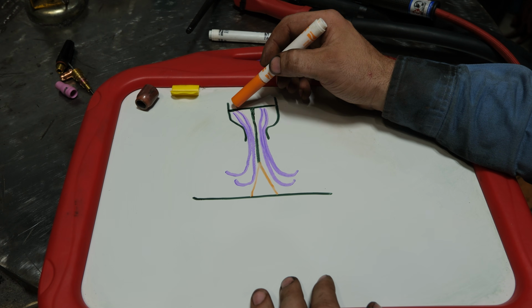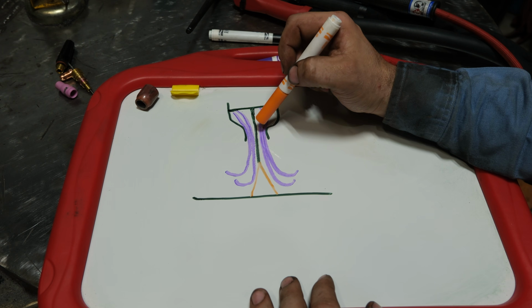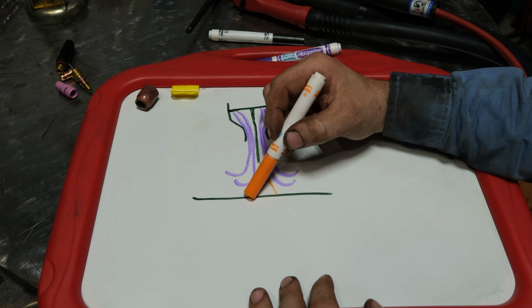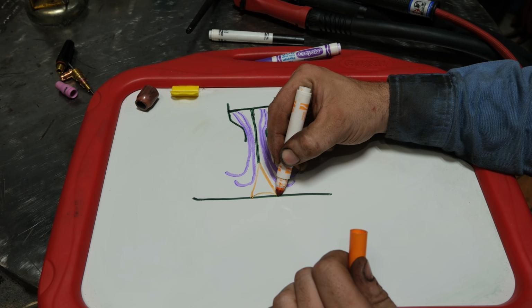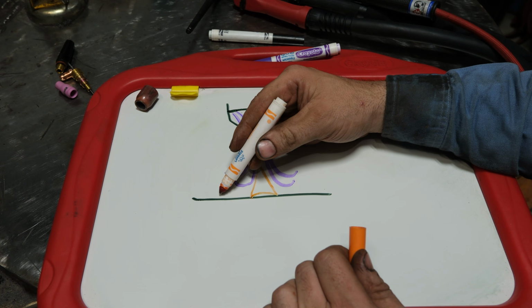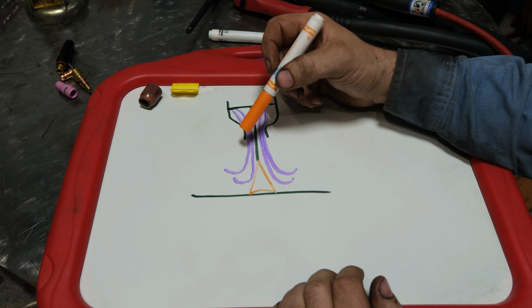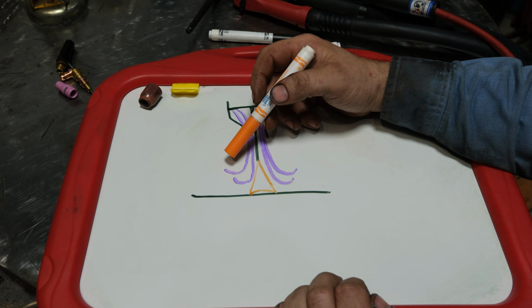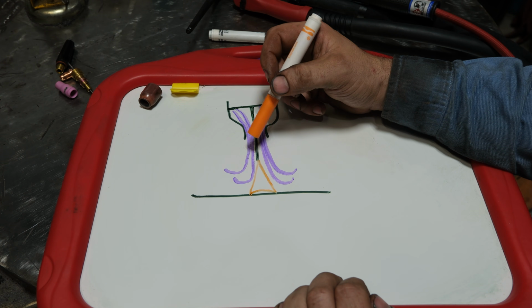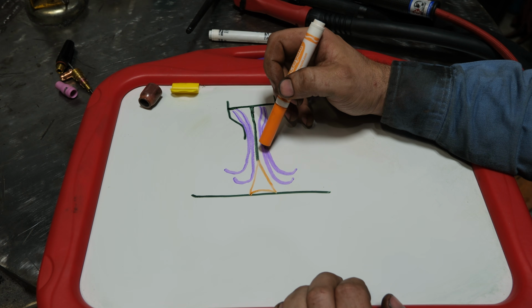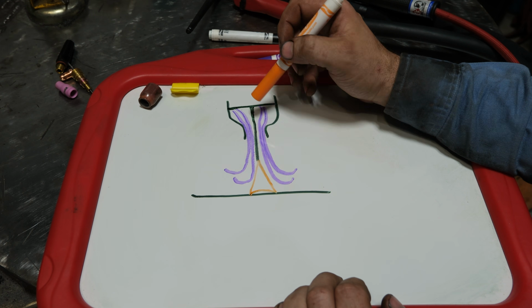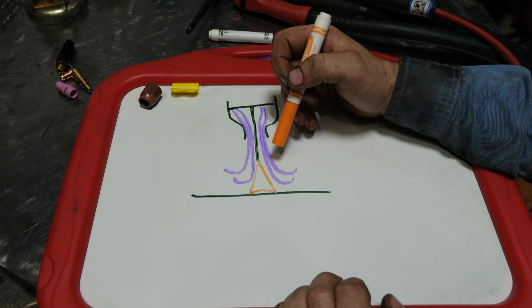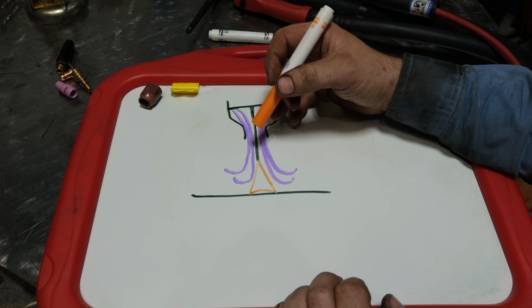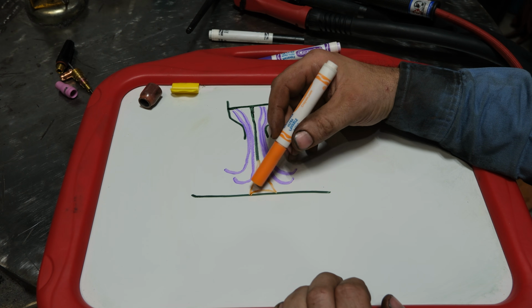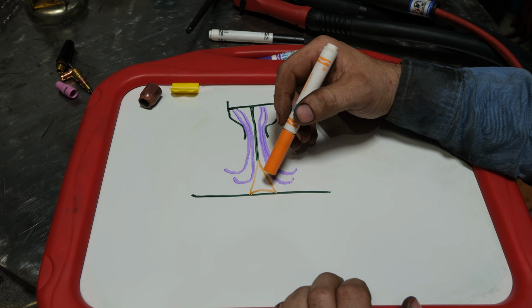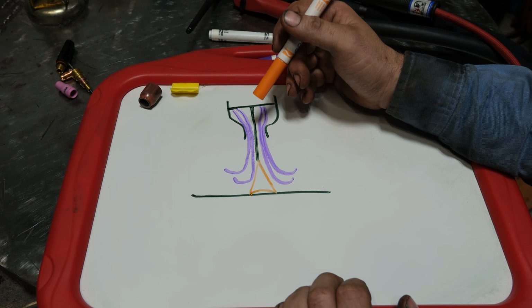Now the shielding gas comes out and actually shields not only the tungsten, not only the weld pool, which would be depicted like right here, but it also shields this area around here, and that becomes very important when welding reactive metals like stainless and titanium, which are very reactive with oxygen, where you need a lot of shielding gas. Well, this purple shielding gas here shields all that, and argon, being that it's inert, more or less just keeps oxygen out of the area that would otherwise contaminate and react with your molten metal or the red hot tungsten.